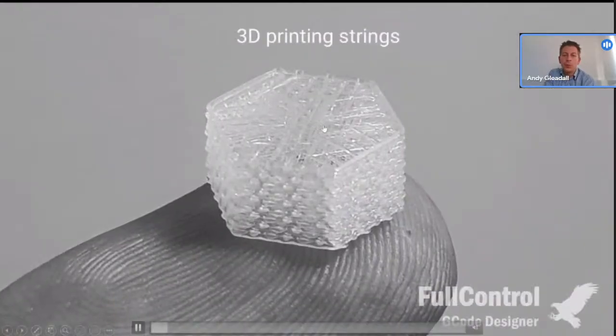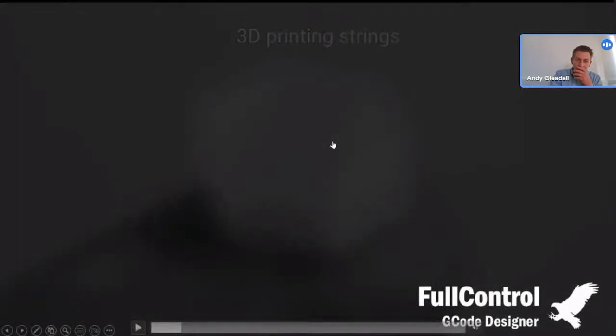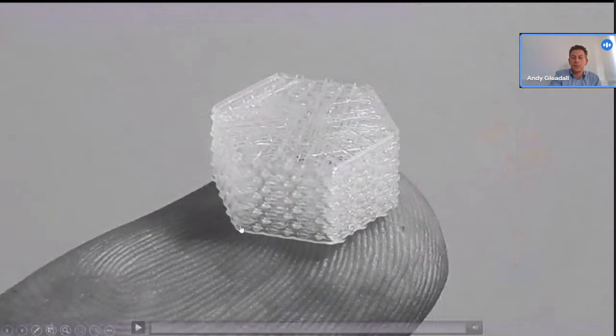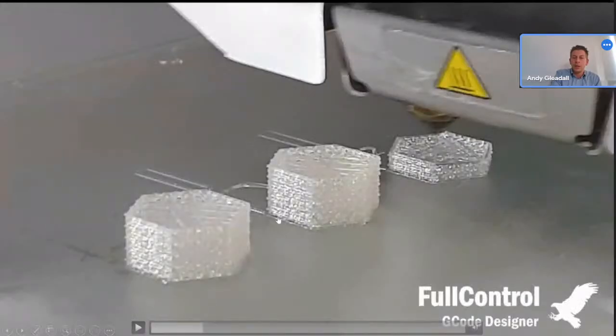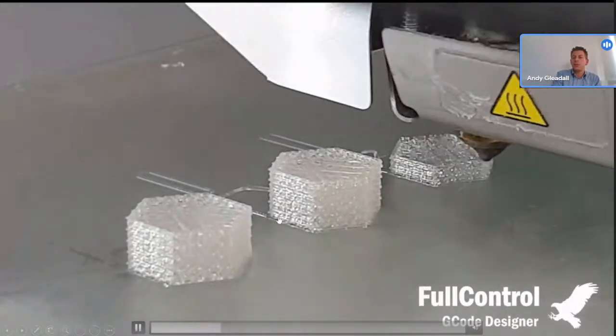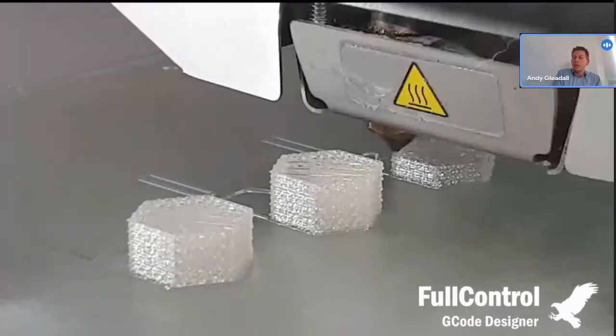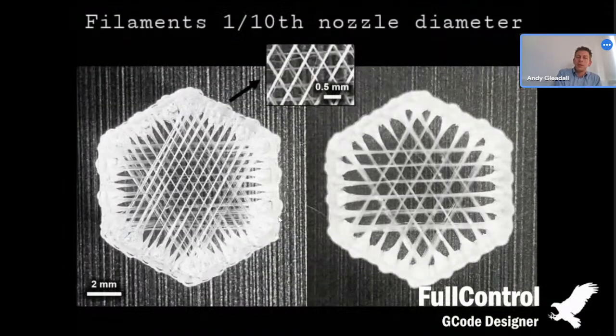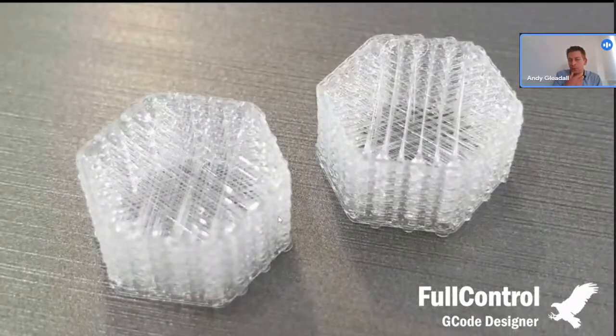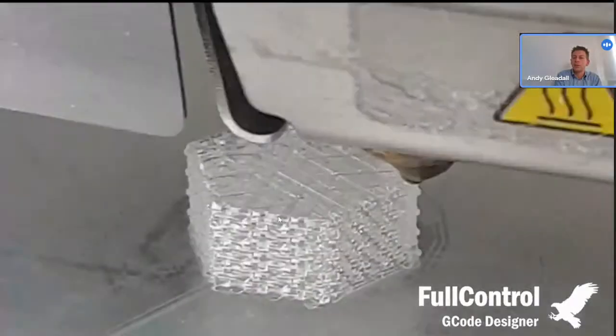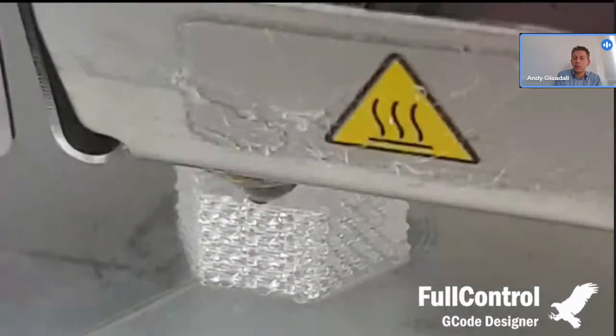So then for some more unusual things, the stuff I've talked about so far is mostly normal type structures, but when you're also designing the print path, you can do completely different types of geometries. So here, this is printing strings, and you'll see just moving the nozzle around really quickly and depositing these strings, and these strings become down to 1/10 of the nozzle diameter. They're obviously highly aligned polymer chains, so the mechanical properties will be completely different.